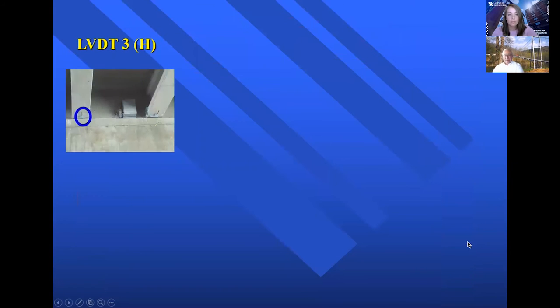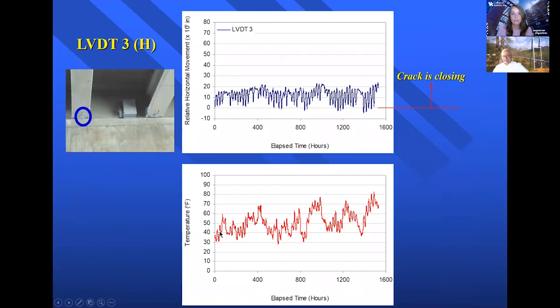And what we found out is that the red line is how temperature increases, and the blue line is how the crack is moving horizontally. So the crack was constantly moving, and actually you can see it with the naked eye if you are standing under the roadway. I-65 trucks are constantly on it.